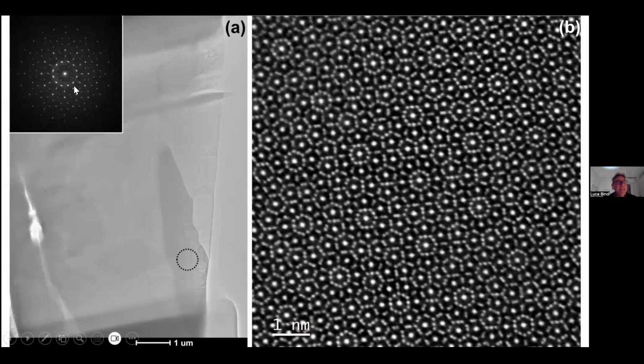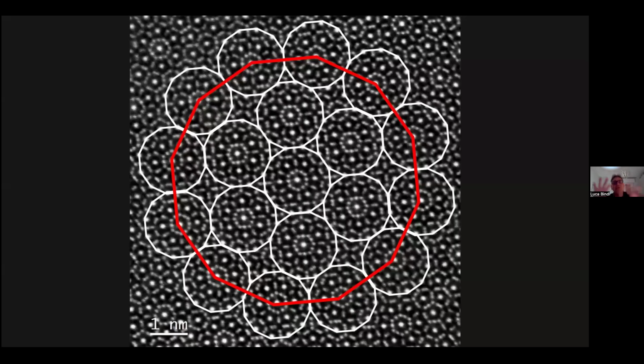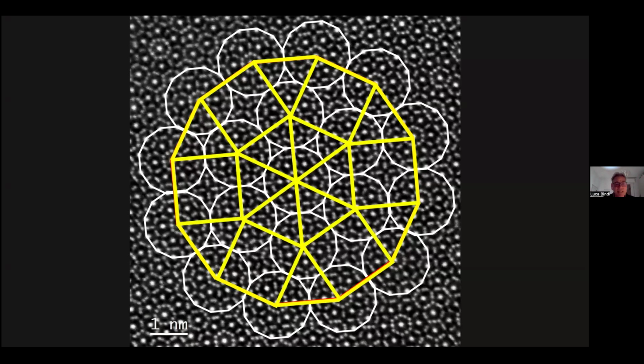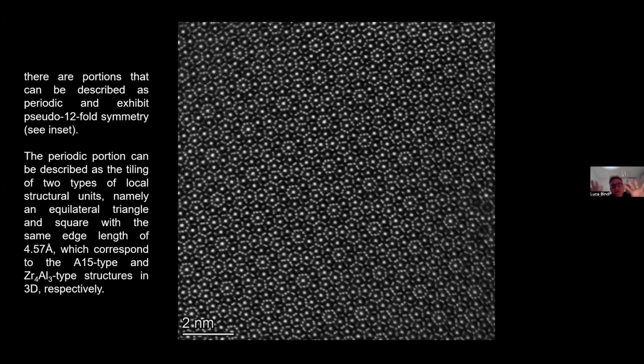to be a perfect dodecagonal symmetry. So we have a perfect dodecagonal quasi-crystal. Look at the high resolution image, which is pretty impressive, because if you try to decorate the high resolution image, you can see that it can be decorated with small white dodecagons, thus forming a large red dodecagon, which is pretty impressive. And if you try to decorate with a classic motif of the dodecagonal quasi-crystals, you get something like this, which is incredible.